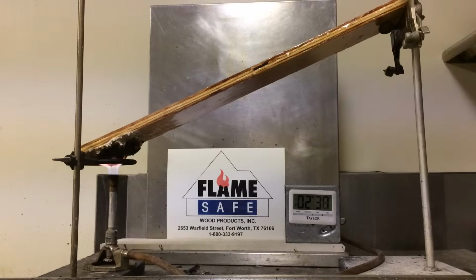FlameSafe Fire Poly FP75E is a highly intumescent coating. At the completion of this test, we will actually measure the height of the intumescence. The intumescence refers to an expansion of the carbon char in regard to the flame spread. This is very important because this is what insulates the flame from the substrate that has been treated.